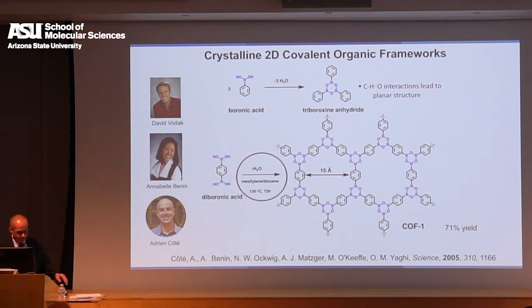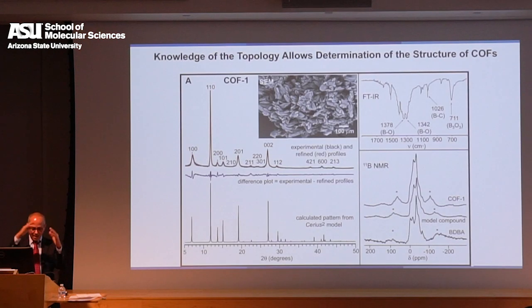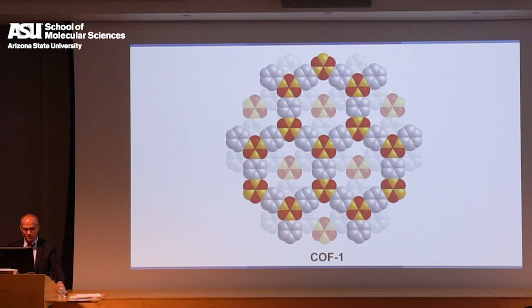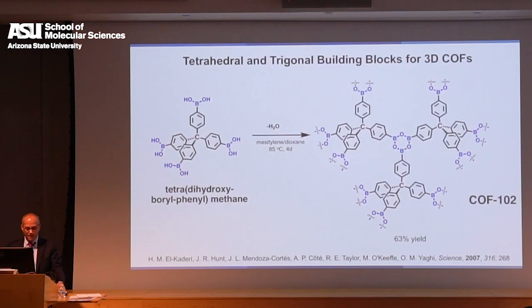And these are the magic conditions where water is produced in this reaction. And because you're running this in a sealed tube, you can control the pressure of water to control the reversibility of the reaction, therefore the crystallization of the COF. I can talk for an entire lecture about the discovery of COFs, because it is a true expression of the importance of the interaction between the professor and the student in a pleasant way. So that hump that I showed you turns into very sharp X-ray powder diffraction. That was COF-1, the very first COF we published in 2005, and this is the structure that we obtained from X-ray powder diffraction.